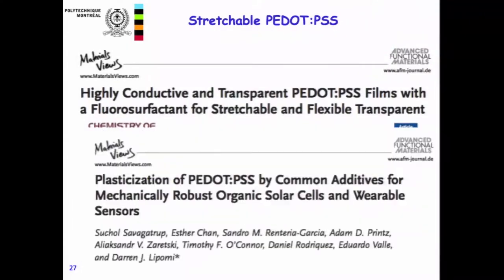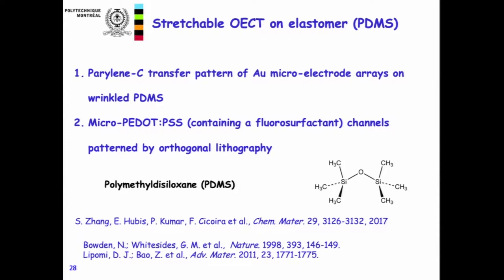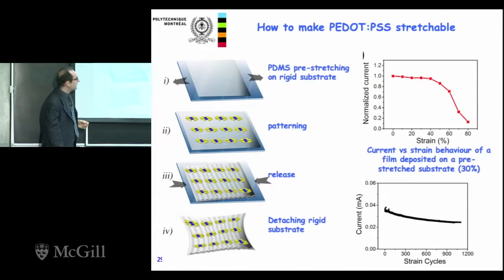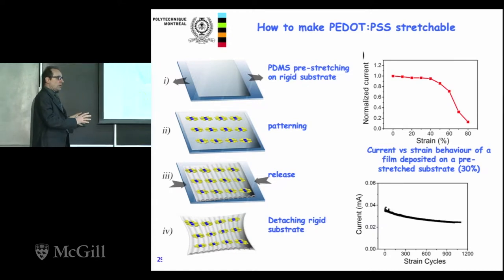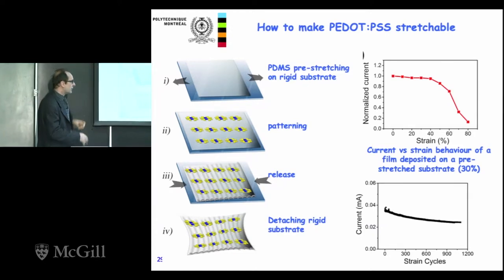So we achieved that. OK, of course, there are many other people working on this topic. We achieved that by setting up a new process. So again, if we want to make a device, you need at least a two-step process, one to make the metal electrodes. Unfortunately, we still didn't find a replacement for metal electrodes in devices, so we still have to pattern metals. And then we have to pattern the conducting polymer. And all this process we made on one of the most conventional elastomers used in research, so polydimethylsiloxane or PDMS. So we were able to achieve flexible, stretchable devices on PDMS. This is one of the strategies we use. Now we are finding other ways to do that.